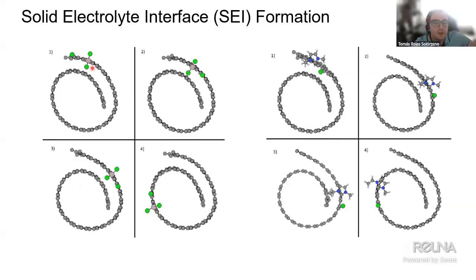An AlCl4, and also ionic liquid, which is also typically used in this type of systems. We can see that the AlCl3 is very easily broken and produces layers of the chlorine that forms in the layers.